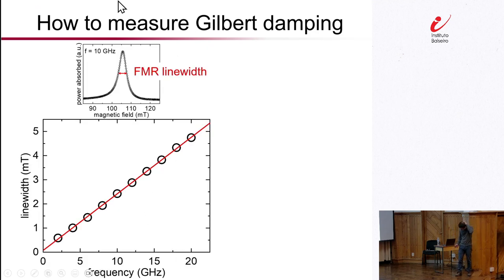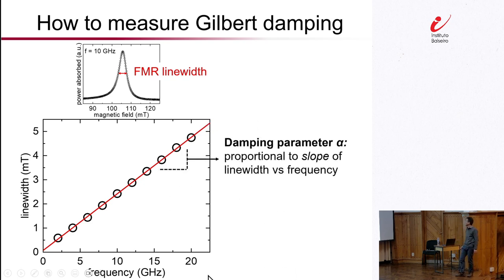All right, so we can do this kind of experiment not just at one fixed frequency, but at multiple different frequencies. In materials that behave very nicely, you would often see this kind of linear response, so the line width changing linearly as a function of frequency. In general, you can see much more complicated responses, but in this presentation, I'm going to ignore all of those. So this is the first order simple picture. In such a case, you can quantify the so-called damping parameter alpha from the slope, because it's proportional to the slope of line width as a function of frequency.